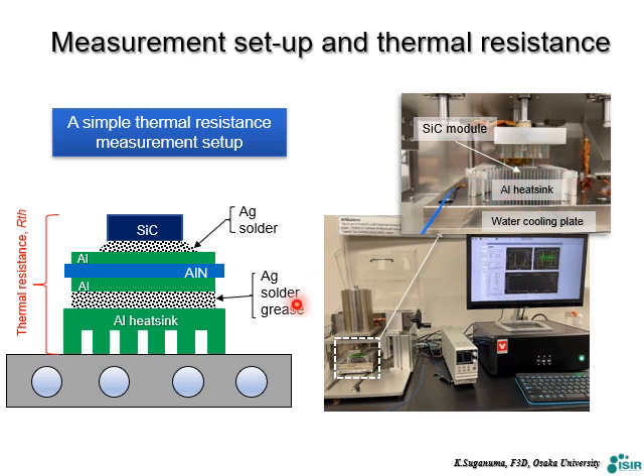You can see a heat sink. And this is showing the schematic. Very simple. So silicon carbide, and in this case, we use the DBA, aluminum base face, and aluminum heat sink. This is one of the typical structures. And we change the die attach material, silver and solder, and the TIM between DBA and aluminum heat sink. We changed the material from silver sinter materials, solders, and grease. This is a typical TIM.